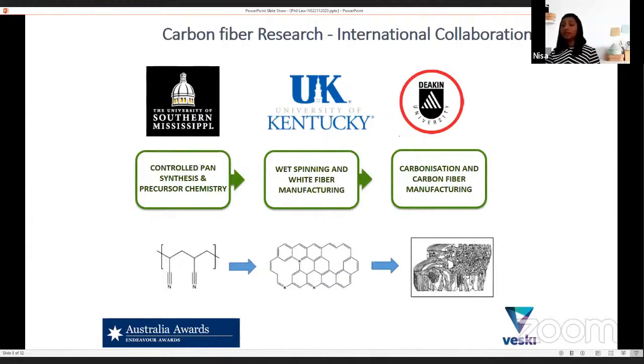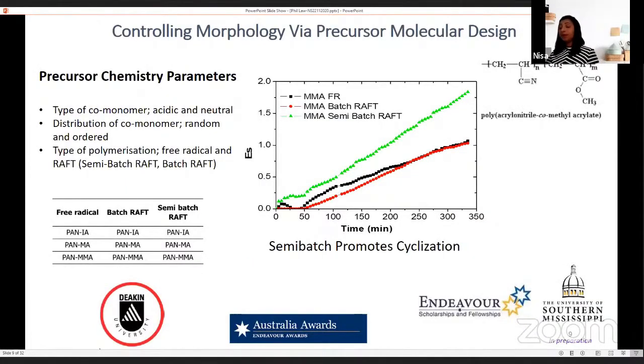So once we design and synthesize a polymer, the next stage is the spinning process to convert the polymers into a white fiber. This wet spinning process involves many steps, and we have to consider a number of process parameters. Again, the exact spinning formulation of these fibers is usually confidential. Then we conducted all the carbonization studies back in Australia. We made a comparative study by selecting 3 co-monomers, and we carried out the synthesis using both conventional and controlled polymerization techniques. We included both acidic and neutral co-monomers in our study, such as itaconic acid, methyl acrylate, and methyl methacrylate. And we used free radical as well as RAFT polymerization methods for the design and synthesis of all these polymers.